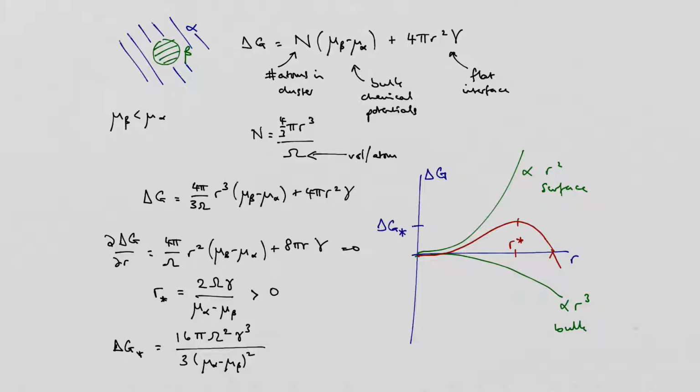Whereas outside the spinodal, the infinitesimal separation is not favourable, so it doesn't happen. You can only make it happen by nucleation, by a random process of assembling something like this, and as soon as you create something finite, it has the interface, and you then have to count its energy, and therefore a major part of the nucleation energy cost is then that area term.